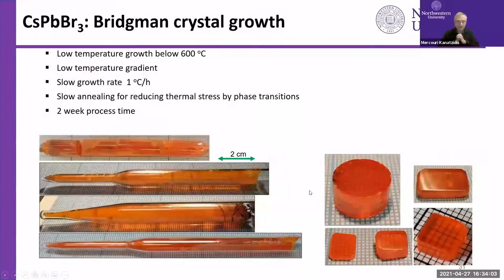So then you can take these crystals and cut them and polish them to size to make detectors or for further characterization. And you see here some of the examples that we have. These are millimeters, so we can make more than 1 centimeter diameter and many millimeters long of any size, basically, you can think of. These tubes are independent Bridgman growth runs, and this is the scale. See here, we have very large scale, and also we can increase the diameter of the crystal as well.